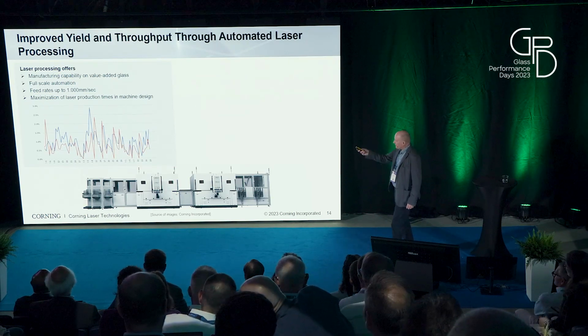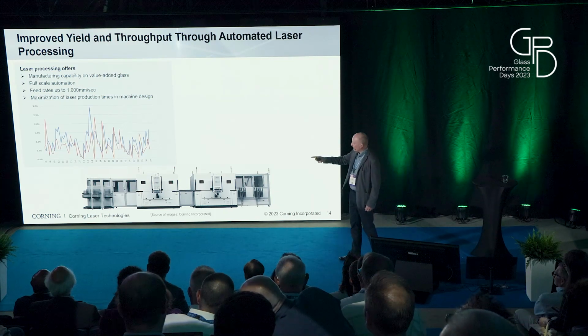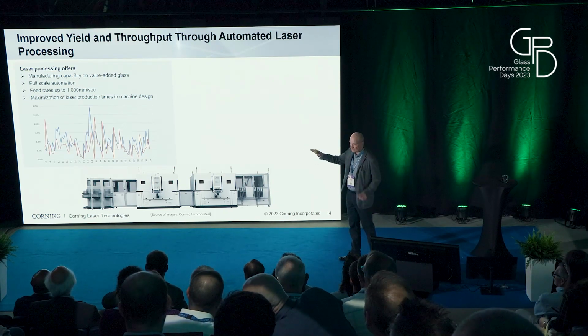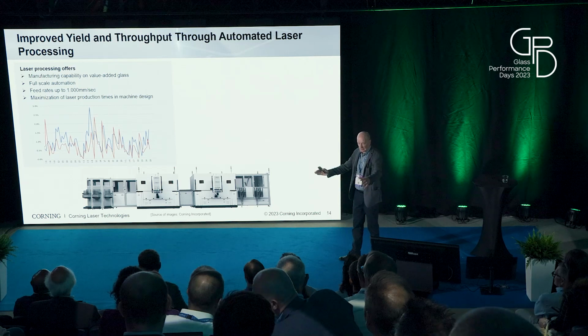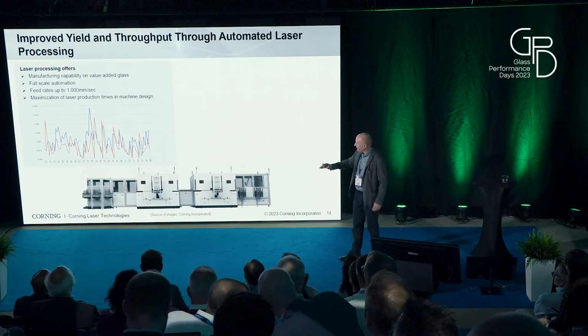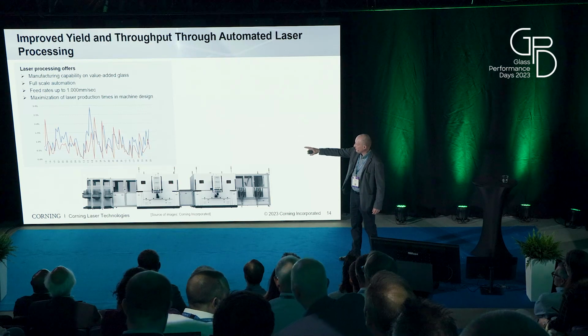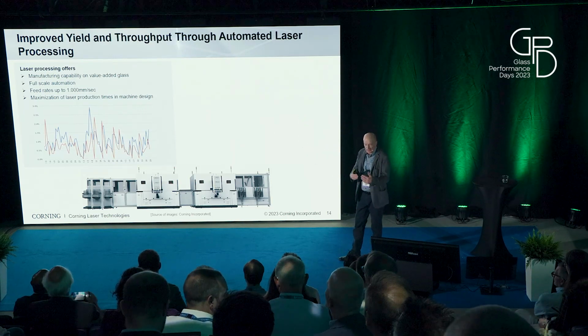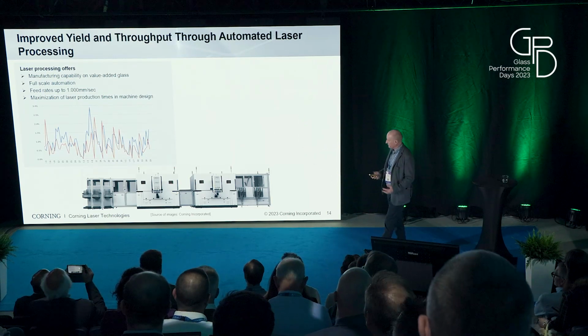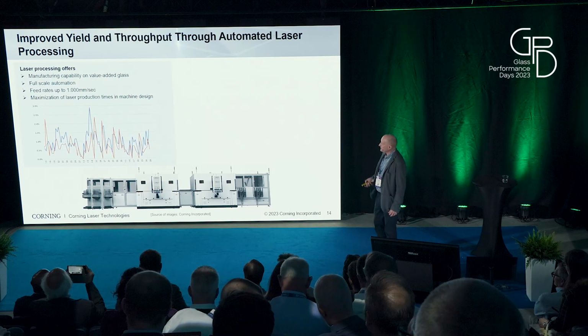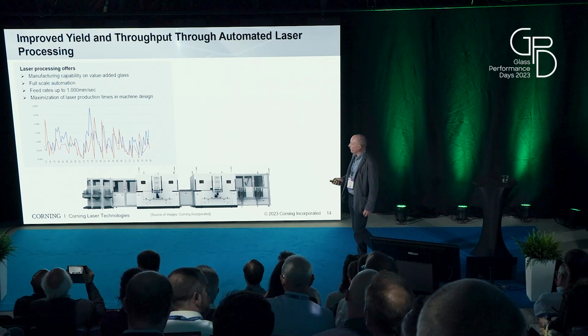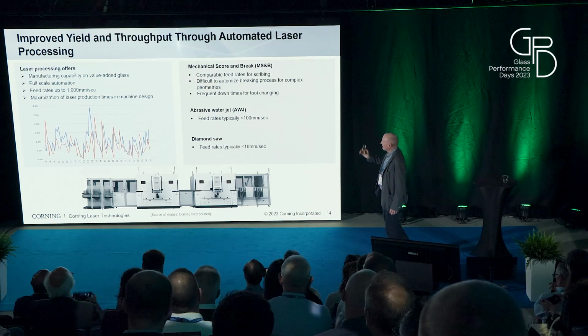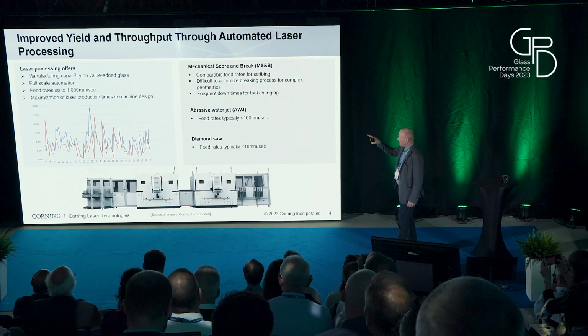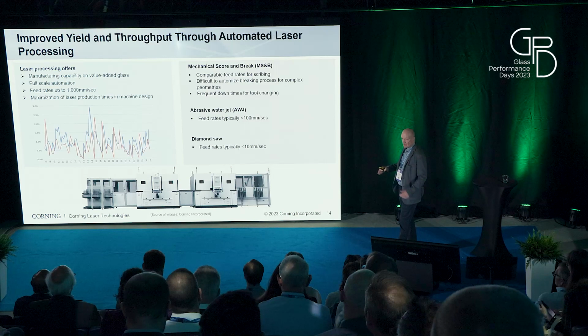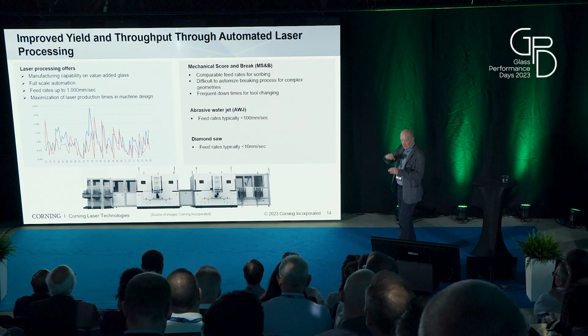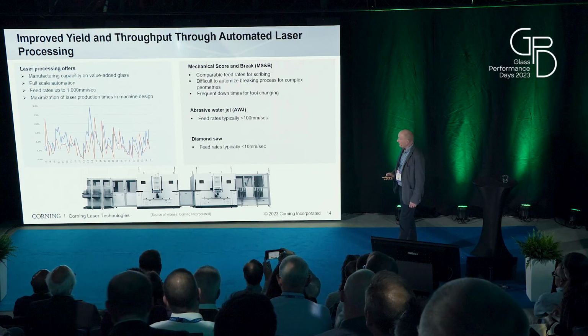These are now real-world numbers. The two graphs show essentially the yield loss of two systems in two production lines. They produce the same parts. And you see that on average, you have around 1% yield loss. That means 99% yield. And typically feed rates in our systems are currently up to 1 meter per second. That compares roughly also to mechanical score and break. But of course, water jet cutting or diamond saw are slower, and even slower when you go to larger material thicknesses.